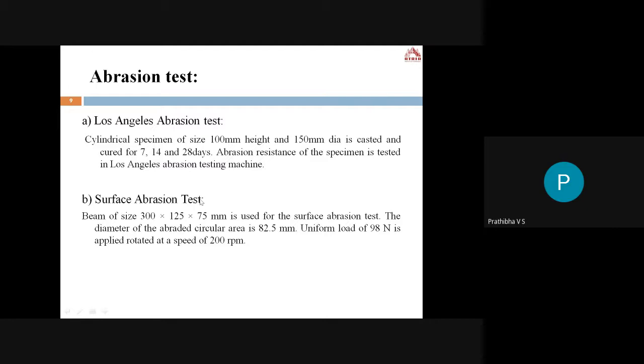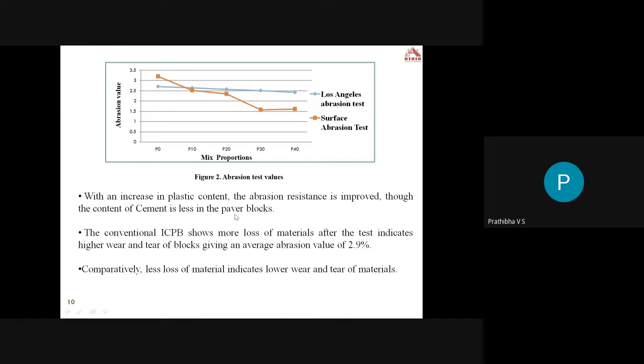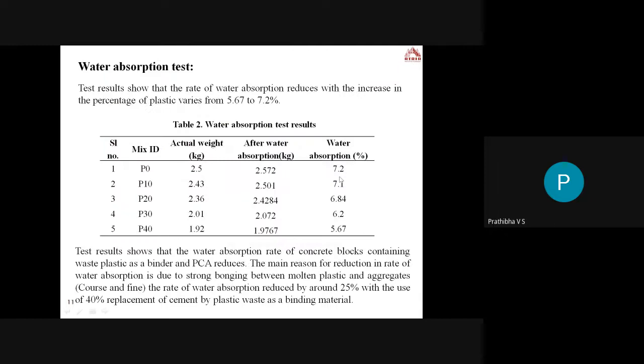Whereas in the surface abrasion test, a beam of size 300 by 125 by 75 mm is used. Here the abraded circular area will be 82.5 mm, the load applied will be 98 Newton, and the rotation will be 200 rpm. The test duration will be around 6 minutes. I'll show you the test results of the abrasion tests here. In both the abrasion tests, Los Angeles and surface abrasion, the results are good.